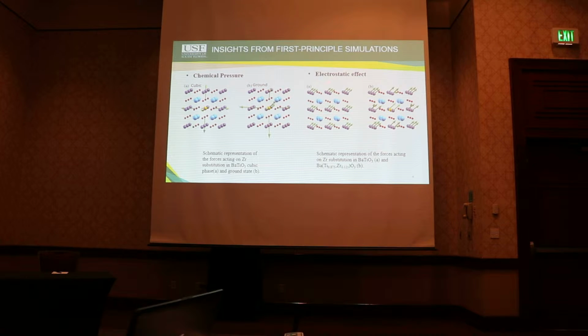The second major insight that we found from the 0 Kelvin simulations is an electrostatic effect. In figure A, we have the pure barium titanate where the green arrows showcase the forces acting on the cell. In figure B, once we've made a substitution for zirconium, not only does zirconium itself not contribute to the collective distortion of the cell, but it also weakens the cell. This interestingly creates two competing effects, as the negative chemical pressure is ferroelectrically favorable, while the weakening of the collective distortion is ferroelectrically unfavorable.